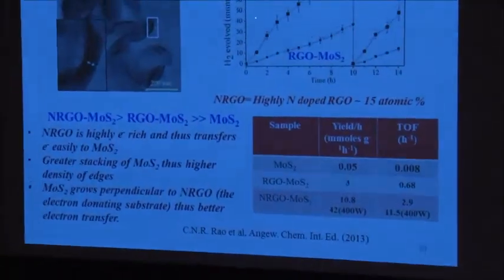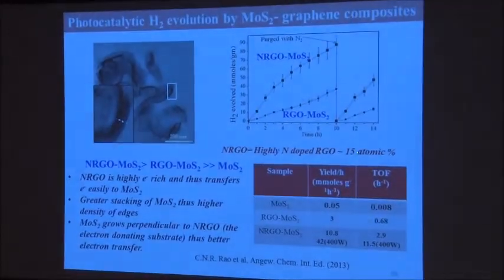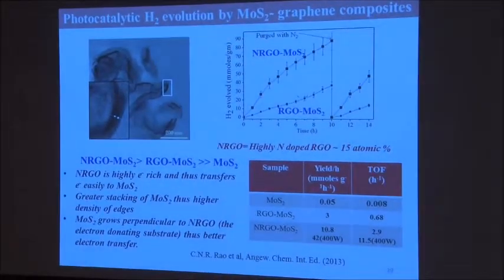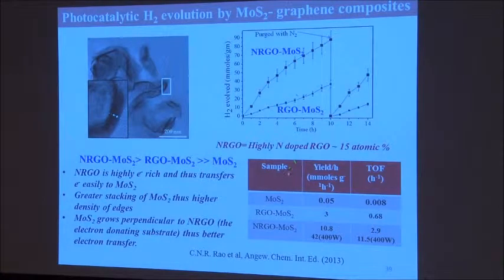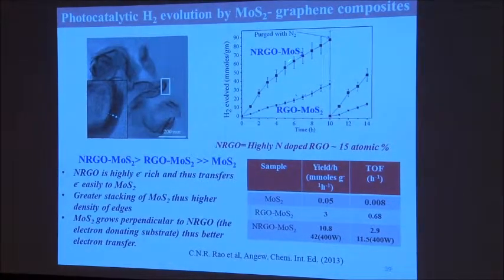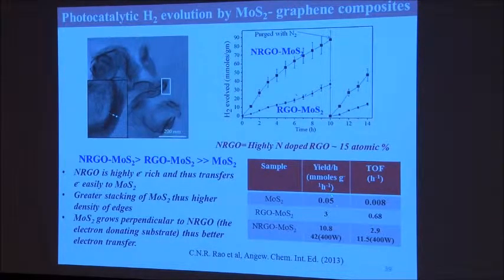That's what actually happens. So if that is the case, I must have a better electron channel. So what we did was, instead of using simple reduced graphene oxide, we highly nitrogenated it. As much as 15% nitrogen we could dope into reduced graphene oxide. Immediately we got very, very excellent performance in hydrogen. What was giving 0.05 millimoles per gram per hour suddenly became 3 in the case of reduced graphene oxide.